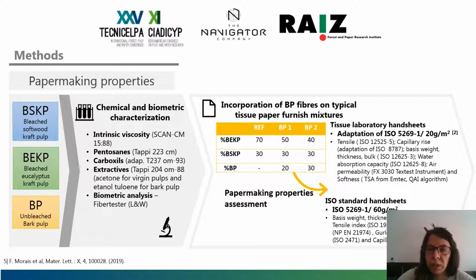To do this, we considered a reference mixture of softwood and eucalyptus pulp, and then two other formulations where we substituted the eucalyptus pulp for bark pulp in 20% and in 30%. With these formulations, we prepared tissue laboratory handsheets, also typical ISO standard handsheets. And these sheets were then analyzed for their papermaking properties.